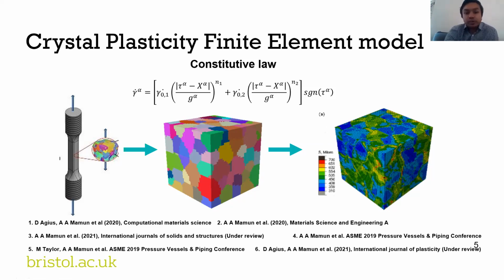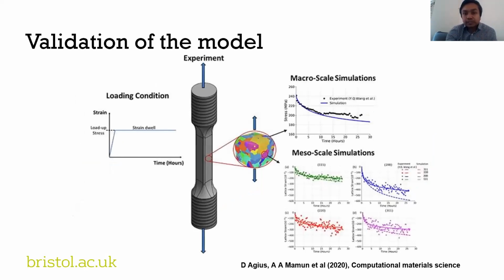So the biggest challenge for this type of modeling is to know whether our model is performing correctly. We can build up this model, we have some assumptions, we can have all these parameters and so on, but how do you know that this model is performing accurately and correctly? For that, we use a few different things because it is a mesoscale model. We are building this from the grain length scale. So only doing an experiment in the lab where we get an average response from our specimen is not enough. But it gives us this macroscopic deformation with which we can compare our model prediction and see if it's predicting accurately. But we also need to know whether the grain response that we are getting in our model is actually a true representation of what's happening inside the material. And for that, we need to go one scale down. So I'll talk about each of these stages briefly.